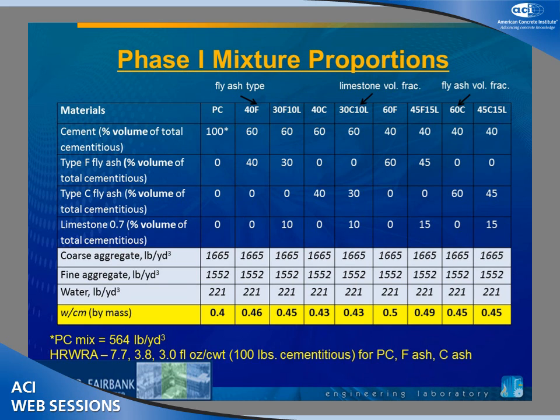These are the phase 1 mixture proportions. You can see the designation we're using across there at the top. So 40F would be a mixture where we replace 40% of the cement with the F-ash. 30F10L would be the corresponding mix where we took some of the fly ash and replaced it with the limestone. Our Portland cement control mix had 564 pounds per cubic yard, and you can see the dosages of the high-range water reducer here at the bottom.